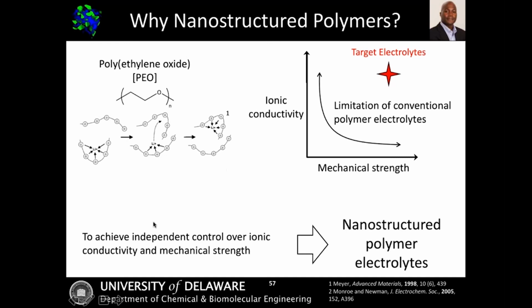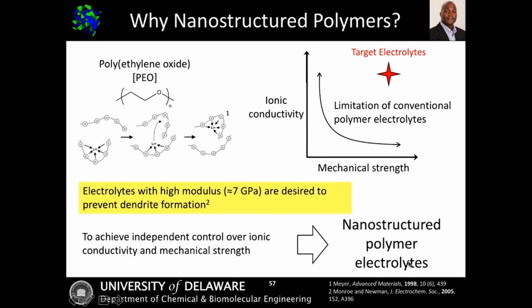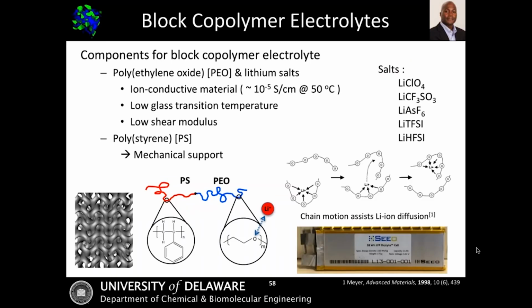And what I'd ideally like to do is achieve independent control over that conductivity and that mechanical strength. One of the ways that I can do that is by forming things like nanostructured polymer electrolytes. In particular, one of the key metrics that people look at is whether I can get electrolytes that have a high modulus, of the order of 7 gigapascals, which has been desirable to prevent dendrite formation. One of the ways to do this, as Joe introduced very nicely, is using block copolymers.